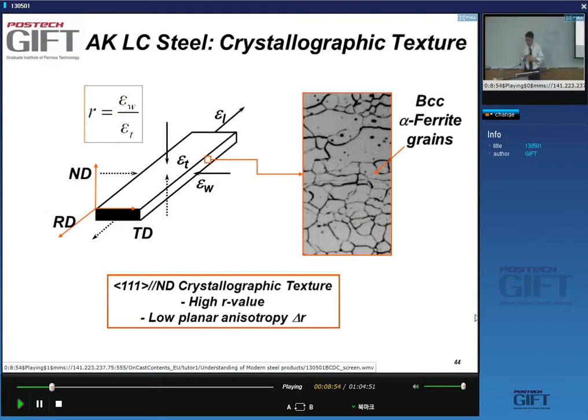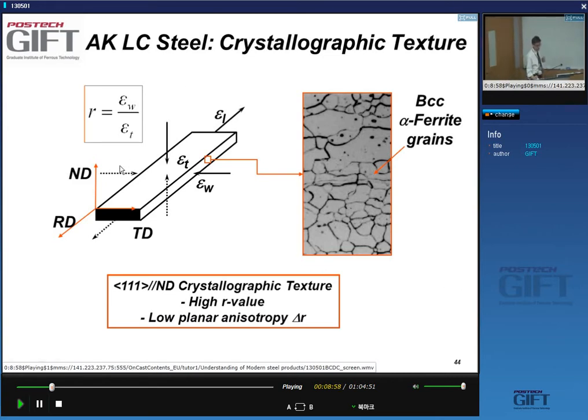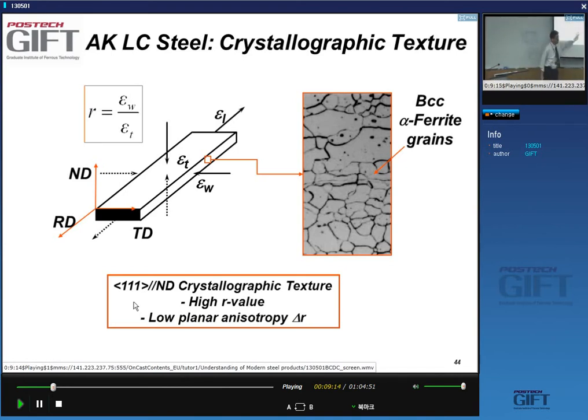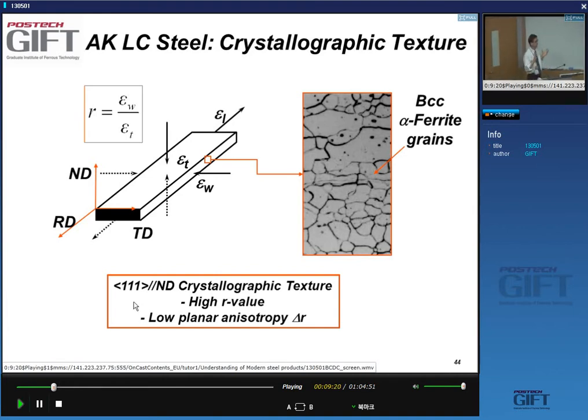It's important, certainly for sheet material, to have high normal anisotropy — the width strain over thickness strain when you test the material. That requires having a lot of grains with a {111} direction parallel to the normal direction of the sheet. Since the orientation in the plane of the sheet is not specified, it's a so-called fiber orientation.